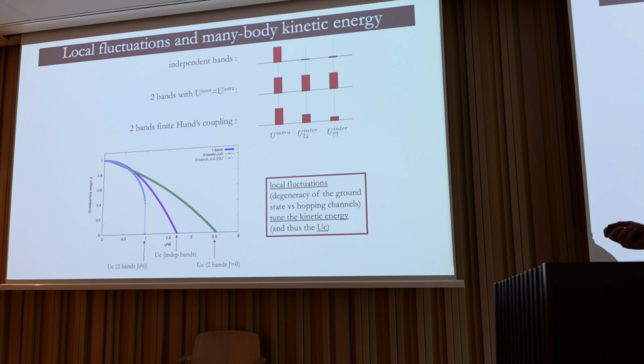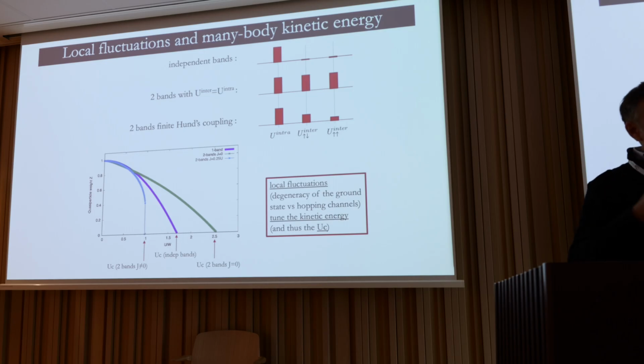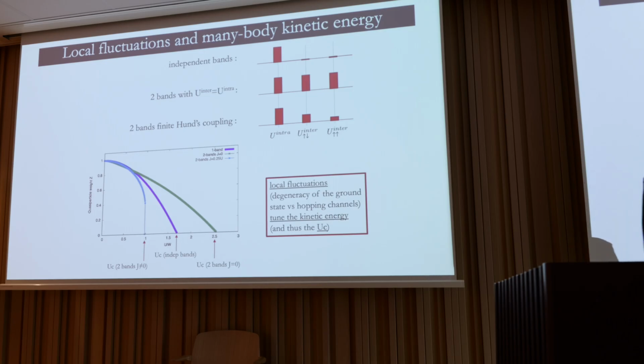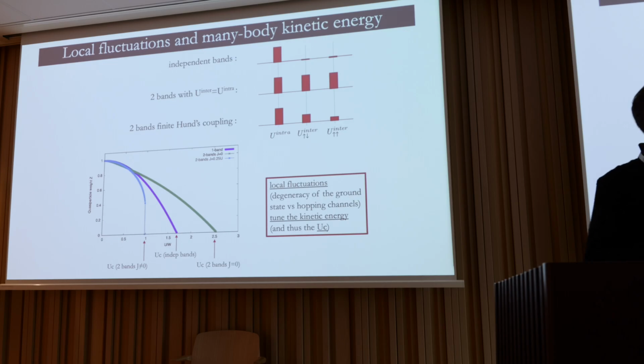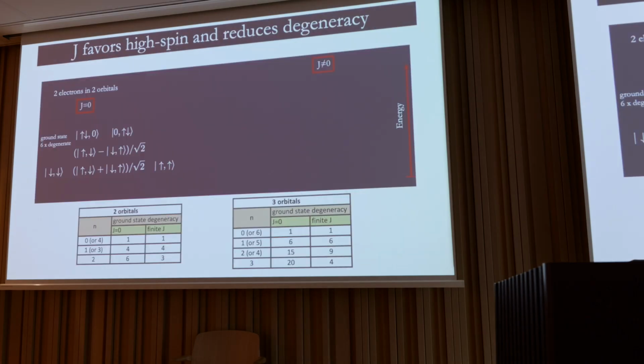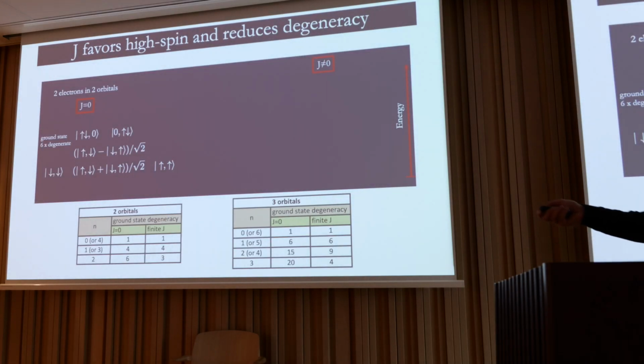If you constrain electrons to align their spins when they find themselves on the same site, you're making their life difficult to hop around. These constrained local configurations that get selected increase the correlations, and so increase the mass. This is one effect—the other effect, well, this is just a cartoon.